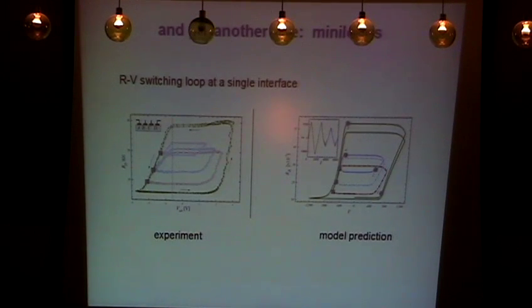So in order to finish, I'm going to show you some work in progress, which is another non-trivial test for this model, which is the mini-loops. So mini-loops is also a typical thing that you can do on systems with memory. So we start with the usual loop in one of the two interfaces, so we have this high-low computation of the resistance as a function of the voltage. And what we do is, after doing several loops, we stop there, and then we decrease the amount of voltage exposure. And when you do that, you get a smaller loop. If you then stop there, you get a smaller loop, and when you stop there, you get even a smaller loop. So this is also, in other words, the multi-level resistive switching that you can produce in these samples, but now in all the gory detail.